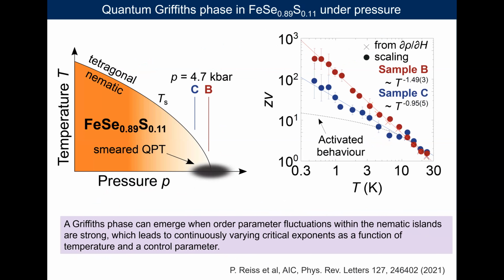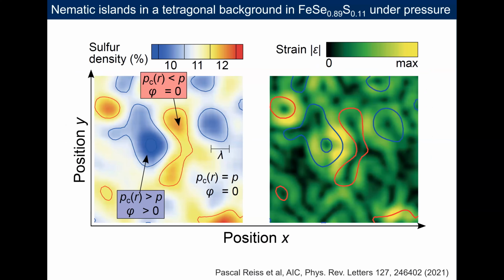the parameters from the scaling, the z nu parameters, had a very strong activated behavior, which is consistent with the presence of a Griffiths-like phase at the nematic endpoint. In a Griffiths-like phase, what happens? You can have very strong fluctuations of the order parameter within the potential nematic islands. Then this will lead to a variation of the critical exponents as a function of temperature and another control parameter, which for us here is strain. It's pressure.